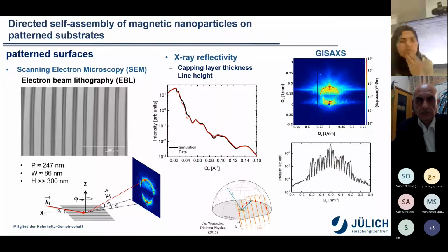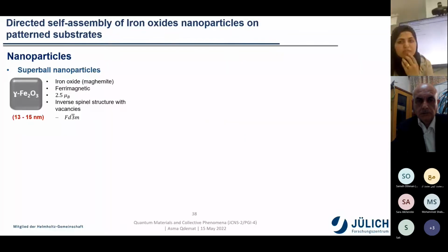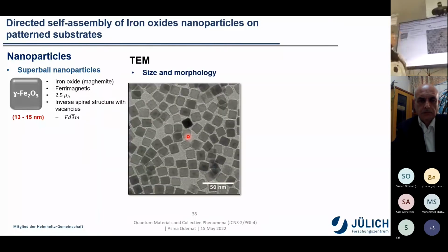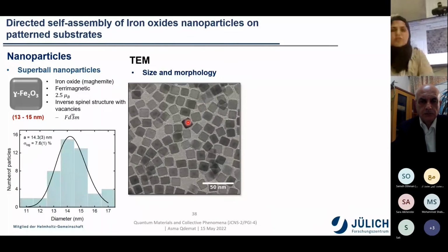The nanoparticles that I use are superball nanoparticles obtained from Sabrina Disch's group at Cologne University. They are maghemite particles, ferrimagnetic, with an inverse spinel structure with vacancies. Characterized using transmission electron microscopy, we can see that these particles do not have any specific shape. They are not exactly cubic with defined edges, but some of them are cubes with rounded edges. To calculate the size and the size distribution, I did the analysis manually, and we obtained a particle size of 14 nanometers and a size distribution of more than 7%.